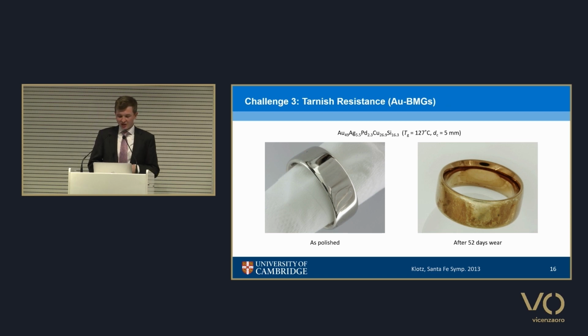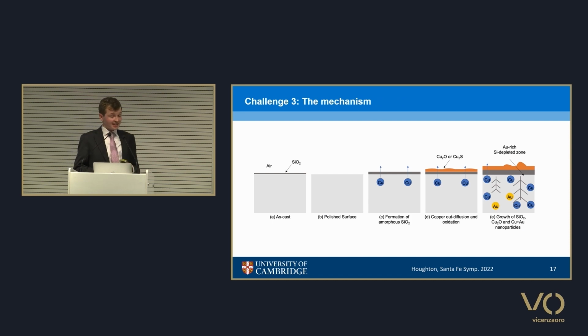So we now move on to the issue that Ulrich didn't concern as much, and that's in these white gold alloys. The alloys are white in general because of their high silicon content. But unfortunately, these alloys tarnish abnormally fast. So this is a sample, a white gold ring that's just been worn for 52 days. And as you can see, there's a dramatic tarnishing phenomenon going on. Extensive work has been done to characterize these systems in general, and the tarnishing mechanism is widely understood.